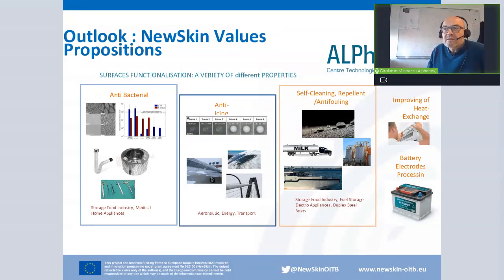The first is antibacterial. We observed that the structures we are able to generate reduce the proliferation of bacteria on the surface. We evaluated a factor of 10 to the power 3, so a factor of 1000, which is very important. Surfaces which are textured reduce the proliferation of bacteria by a factor of 1000.